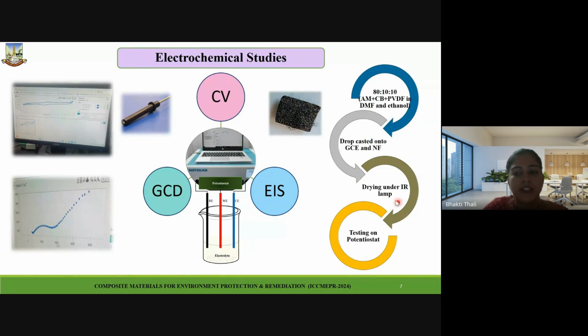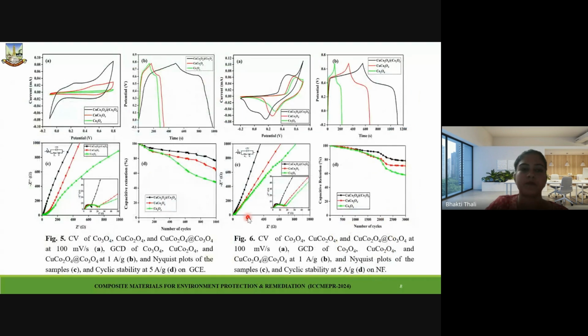Further, it was subjected to drying under an IR lamp, and testing was done on the potentiostat using a 3-electrode system: reference electrode, working electrode, and counter electrode. For the measurements, CV, GCD, and impedance were carried out. As we can see, Figure 5A and 6A correspond to the cyclic voltammograms of all the three materials. Figure 5A corresponds to readings taken on glassy carbon, and Figure 6A corresponds to the readings taken on nickel foam.